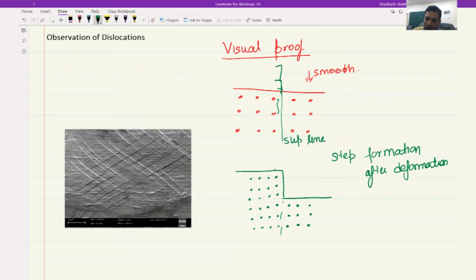And this is an SEM micrograph, and what you see here, these lines, are basically slip lines where tens of thousands of dislocations have accumulated, and when they ended up on the surface, you were able to see a large step. These were not happening just along this direction, but also along this direction. Eventually it becomes so large that we can observe it with naked eyes. If you polish it again, it will go away, and if you deform it again, or cause any other type of deformation where dislocations have to move and come to the surface, you would again be able to see these. If you keep polishing, it will keep disappearing, and if you keep deforming, you will see them again, and this will also be observable in your tensile samples.